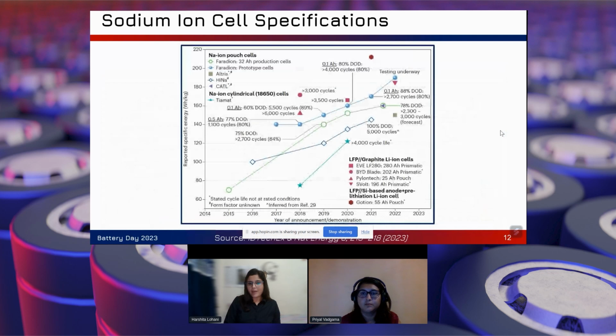If we compare these sodium ion cells with the currently existing LFP-based lithium ion cells, we find that the sodium ion cells are comparable in performance to the LFP-based lithium ion cells where graphite has been used as the anode. Whereas the cells where silicon, the next generation anode, has been used on the anode side have a very high energy density. And the Faradion prototype cells, which are in testing, are claimed to reach up to 190 watt-hour per kg at the cell level. These cells can then go far beyond the performance of the LFP-based graphite cells as well.